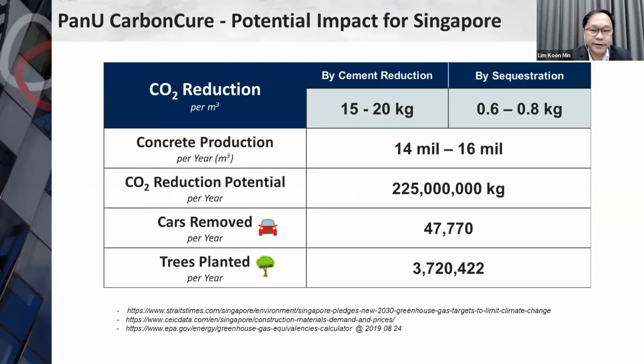Now look at a scenario playing out for Singapore concrete production numbers. On the left, when you look at the cement reduction, essentially we are reducing between 15 to 20 kilograms of CO2 per cubic meter. And how much is being sequestered is 0.6 to 0.8 kg. So altogether, when you talk about 14 million to 16 million cubic meters of concrete production a year in Singapore pre-COVID, the potential reduction and avoided CO2 we are looking at is 225,000 tons of CO2.